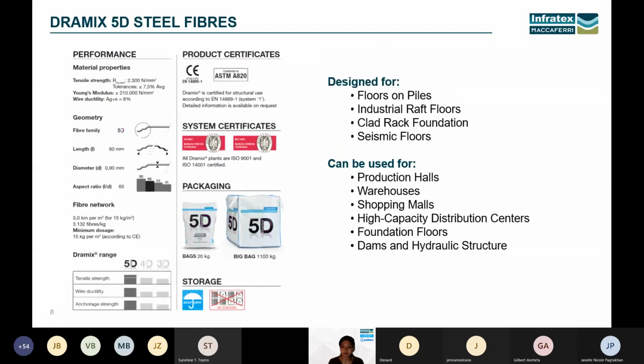Okay, so for the 5D fibers, with a tensile strength of 2,300 Newton per square millimeter, with its length of 60 millimeter and the diameter of 0.9 millimeter with an aspect ratio of 65, it can be used for foundation floors with floors on piles. So we normally recommend to use this for seamless floors. Seamless floors are a combination of steel fibers and rebars with continuous pouring. So with no more construction joints and contraction joints, no more sockets also.